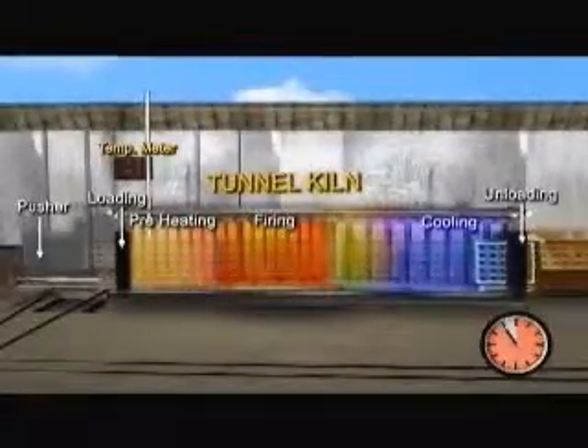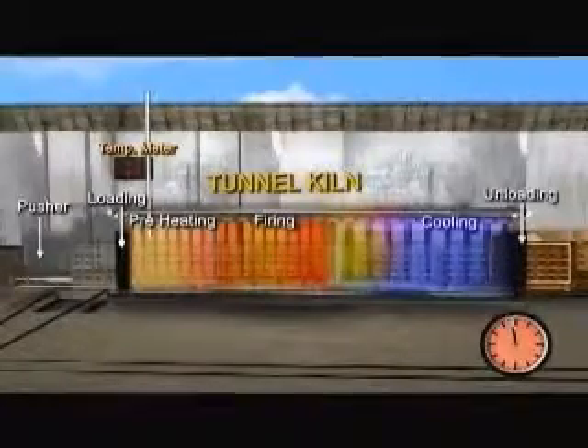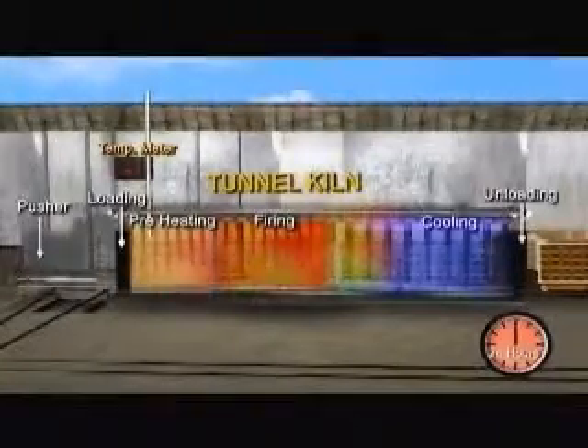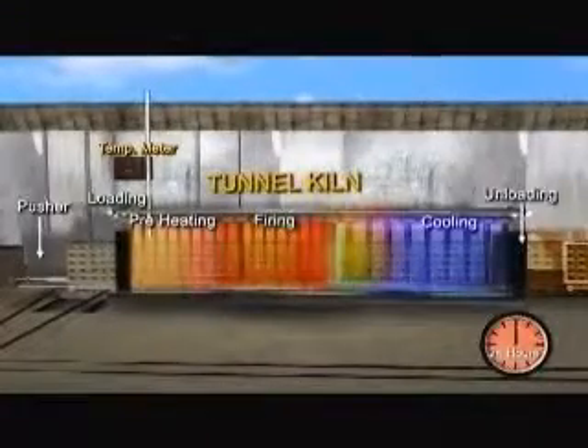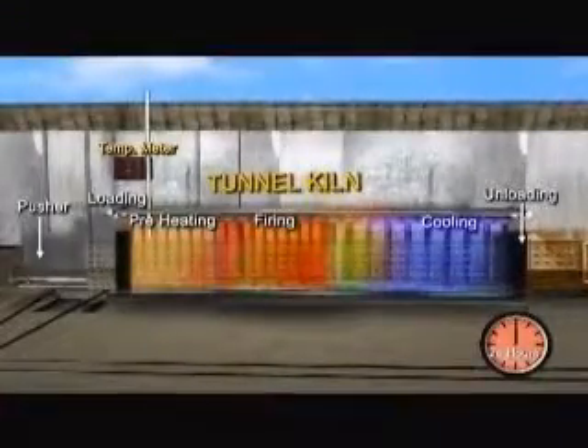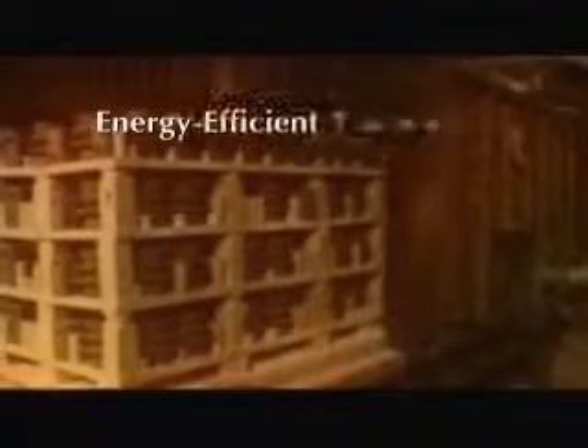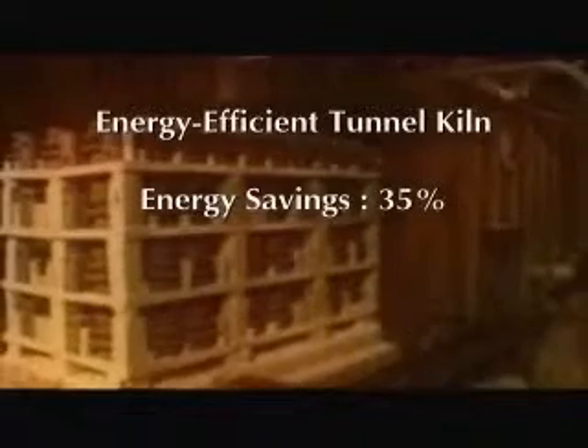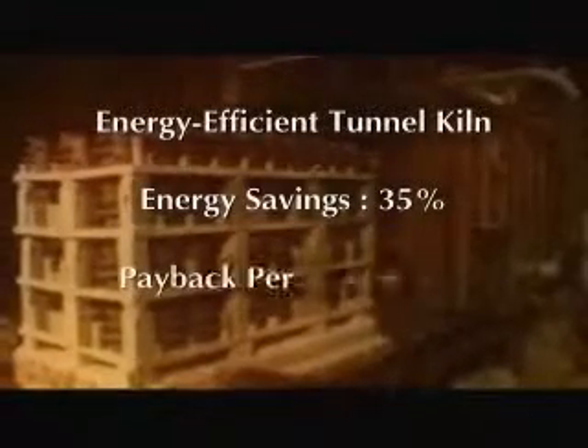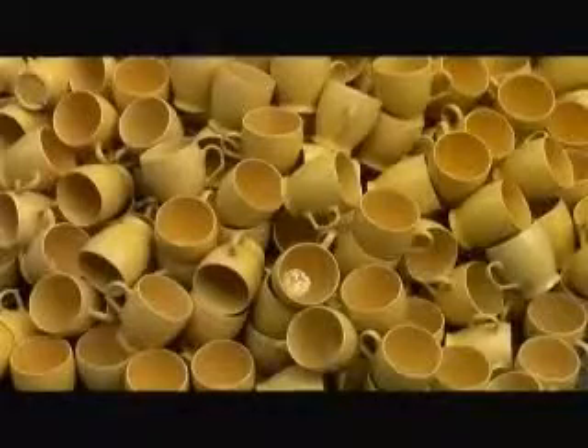A trolley usually takes 24 hours to move from one end of the kiln to the other. Nearly 30 trolleys travel through the kiln in 24 hours. As the tunnel kilns run continuously round the clock and the firing time is lesser compared to downdraft kilns, the productivity of the units has gone up tremendously. In terms of fuel costs, tunnel kilns are 35% more efficient than downdraft kilns. The payback period is around 5 years. Due to temperature control and uniform heating, the quality of wares has greatly improved. With the absence of coal, air pollution has also gone down significantly.